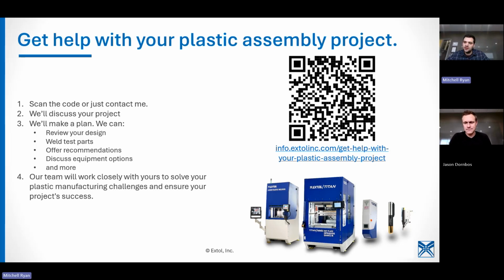Tom asked, when would one prefer hot plate welding over other welding processes like ultrasonic or vibration? Is it usually cheaper? There's a couple of different reasons. I'll speak to ultrasonic first and then vibration after. Typically with ultrasonic, there's a size requirement. Once you get past a certain size, getting the energy into the energy director without blowing out in other areas of the part gets pretty challenging, especially with some materials like polypropylene, where directing the energy becomes a bit challenging with those larger parts.